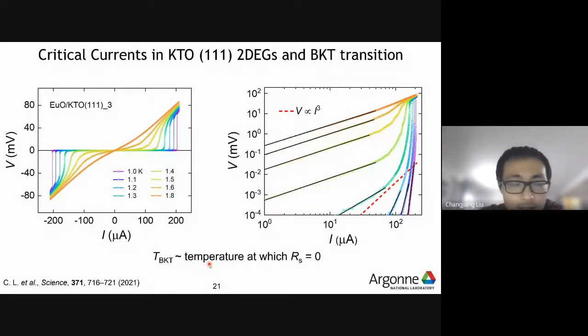So we further did the critical current measurement near the transition temperature. You know, for a 2D superconductor, there is an additional phase transition called the BKT transition, and this is due to the formation or dissociation of vortex, anti-vortex pairs in two dimensions, and that can create a power law dependence of voltage on current. So we found that this system indeed showed a BKT transition, meaning near the transition temperature, V is proportional to current cubed. So this red line is at that temperature. This is a cubic dependence, and it happens just around the temperature where the sheet resistance goes to 0.